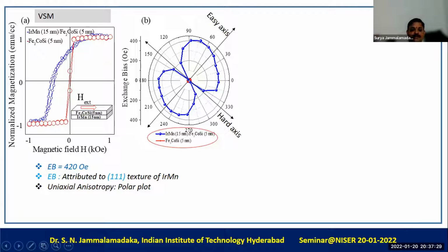It has been predicted that if the iridium manganese is along the 111 texture, then the exchange bias can be induced without field cooling. That is what happened even in our system. As soon as we confirmed the texture of iridium manganese along the 111 direction, because of this texture, we could see a shift of the magnetization loop without the field cooling process.